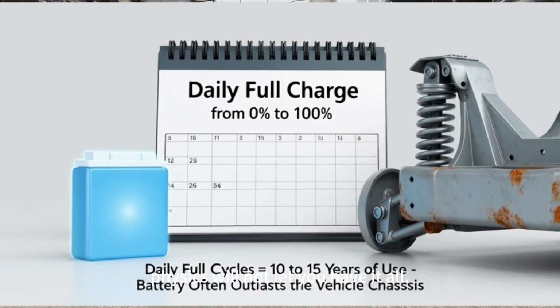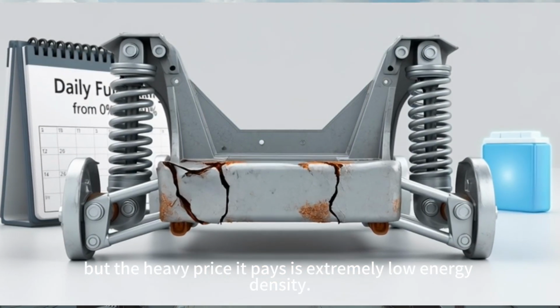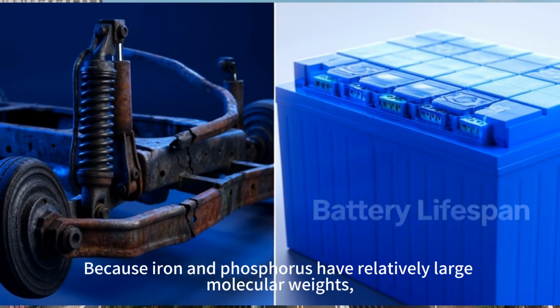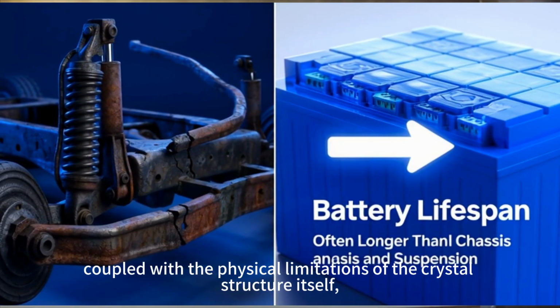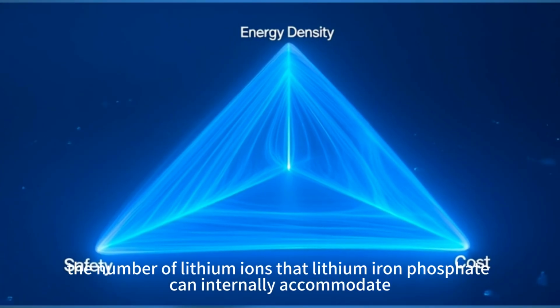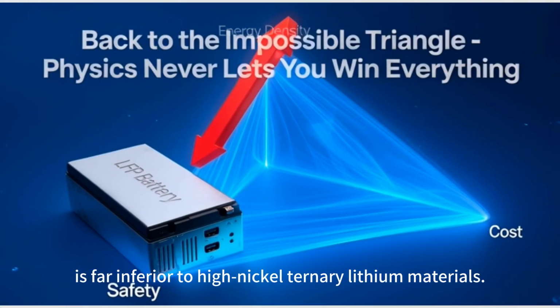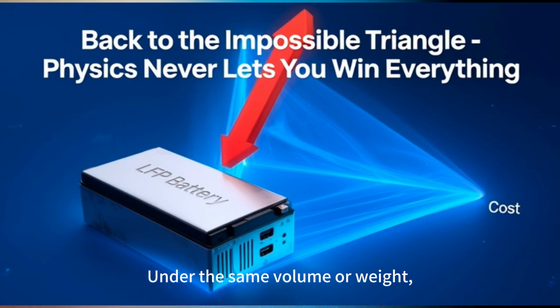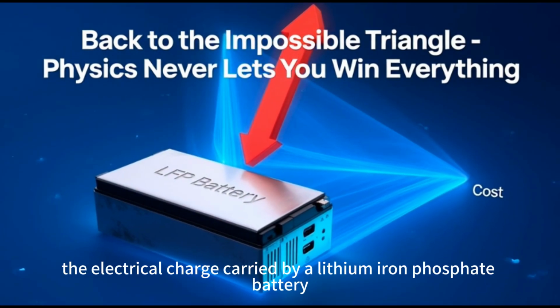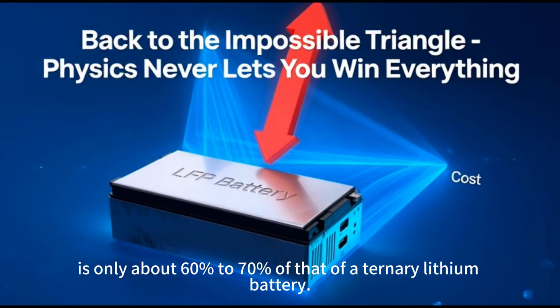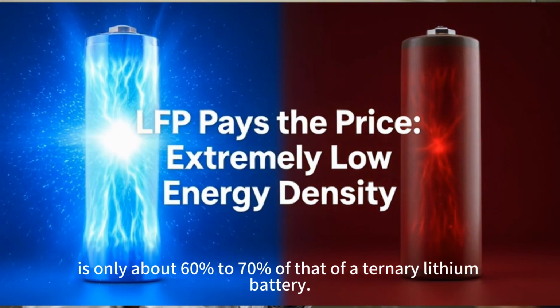However, just as we mentioned at the beginning with the impossible triangle, physics will not let you have it all. Lithium iron phosphate has achieved absolute safety and super long lifespan, but the heavy price it pays is extremely low energy density, because iron and phosphorus have relatively large molecular weights, coupled with the physical limitations of the crystal structure itself. The number of lithium ions that lithium iron phosphate can internally accommodate is far inferior to high-nickel ternary lithium materials. Under the same volume or weight, the electrical charge carried by a lithium iron phosphate battery is only about 60% to 70% of that of a ternary lithium battery.